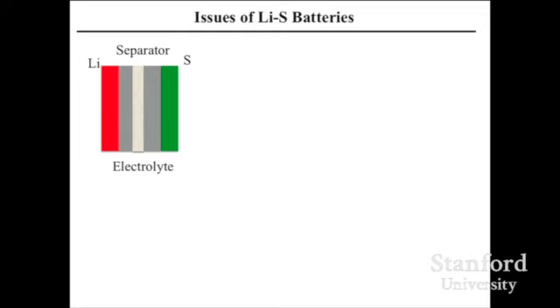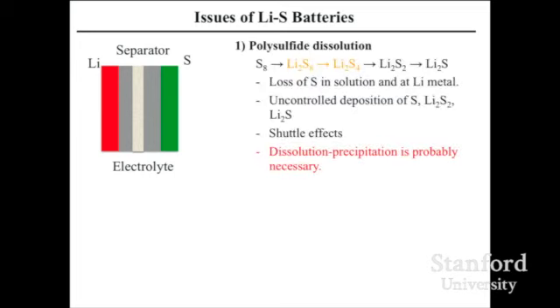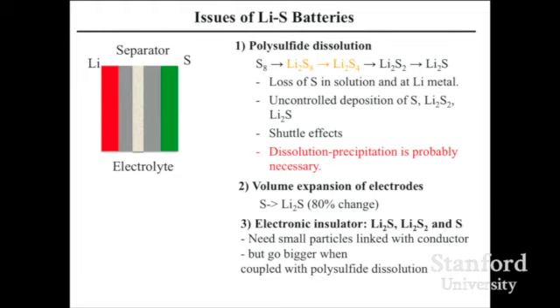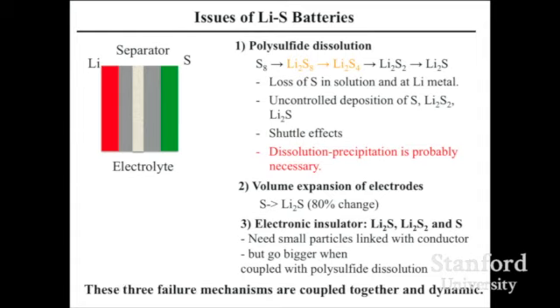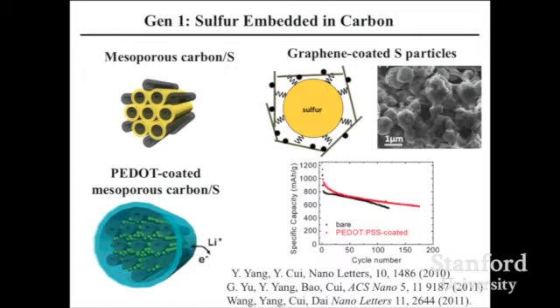What are the problems right here? You have lithium, you have sulfur. And sulfur goes through this S8 molecule, solid, becoming polysulfide, soluble in your electrolyte. You're losing material, so capacity decays very fast. And also the volume expansion is big, 80%. So the lithium sulfide species are not that conducting electronically. Eventually, these three things coupled together really make it a nightmare to deal with. It's so hard to make sulfur work. Now let's come back and really think about how to make it work.